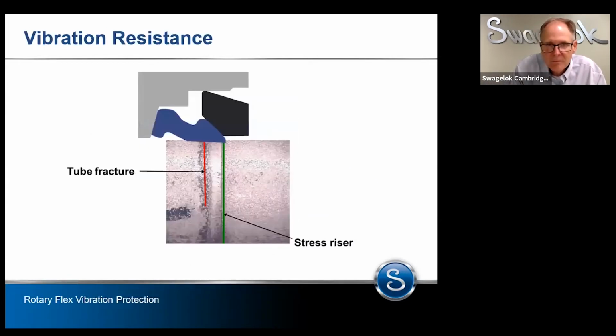This is a tube sample from the extreme rotary flex vibration test, demonstrating how the hinging and colleting action protects the stress riser. After high amplitude accelerated tube vibration, the sample fractured here, away from the would-be stress riser, by virtue of the colleting region provided by the hinging colleting back ferrule. By protecting the stress riser and supporting the tubing in the colleting region, fracture, if it occurs at all, occurs in an uncompromised section of the tubing. This means the life of the tubing was greatly extended.